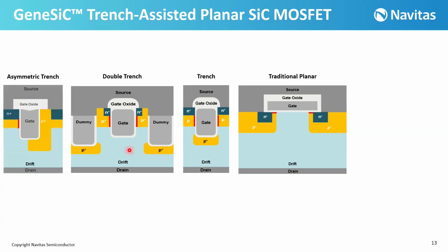And another way is the asymmetric trench. In this asymmetric trench, normally we can sacrifice one side of the cell here on the right-hand side by P plus implantation in order to protect the other side, which is the left-hand side. So if you look at this asymmetric trench, normally this part is active, we have the channel, and the right-hand side is not active. It's just for protecting the left-hand side. For this design, normally we are making the side walls, or it's better to say, having the side walls in the a-face, which has the higher channel mobility.